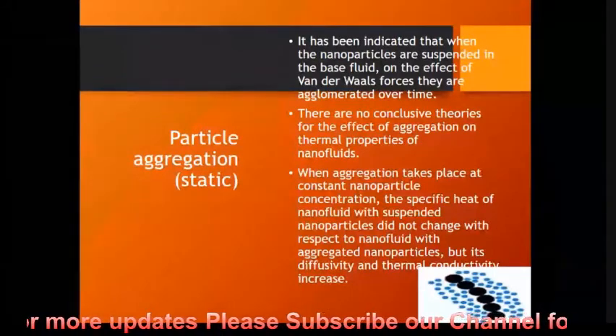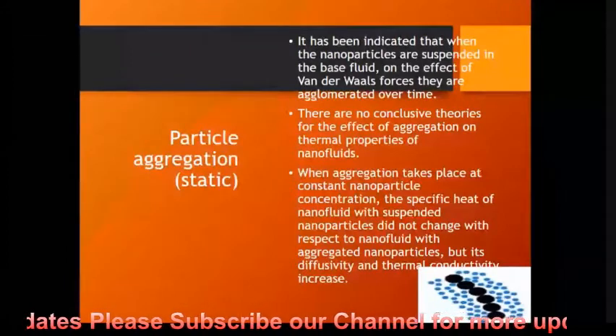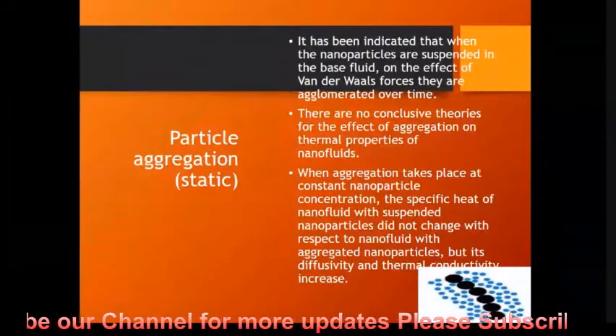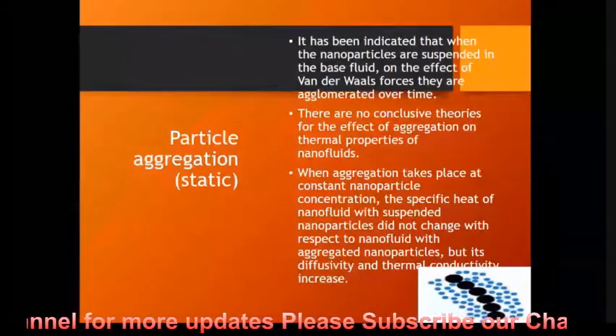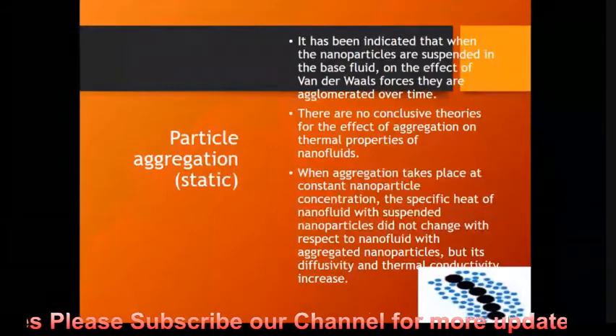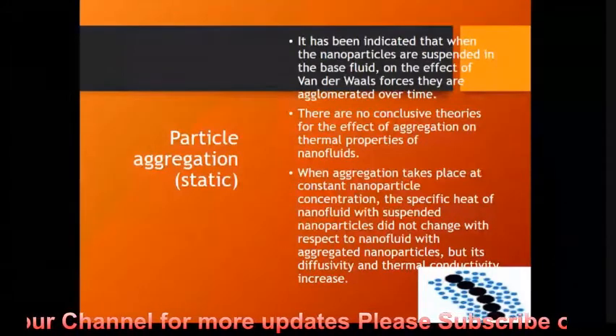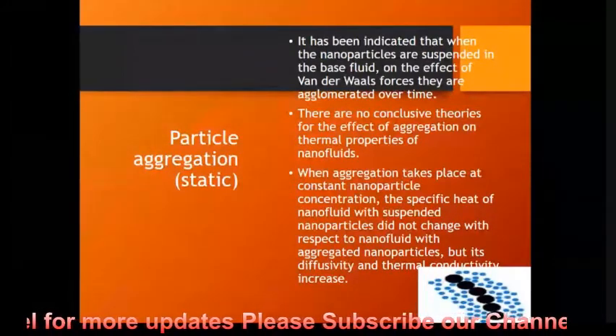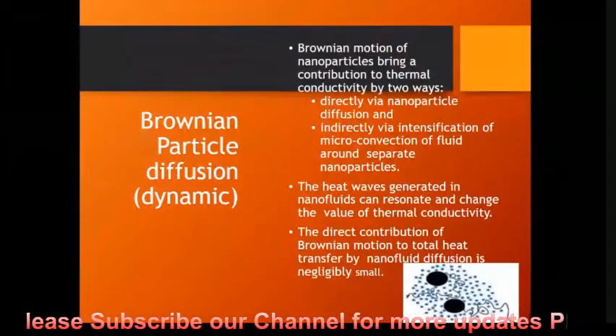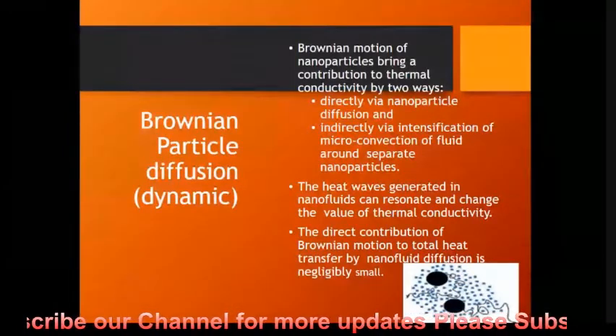So there are no conclusive theories for the effect of aggregation on thermal properties. So aggregation is something different from layering. Of course, layering is a very basic nominal thing to be done as far as the characterization mechanism is concerned. So it's a basic mechanism. We can very well go ahead. But as far as the particle aggregation system is concerned, this mechanism takes place at constant nanoparticle concentration, and the specific heat of nanofluid with suspended nanoparticles did not change with respect to nanofluid with aggregated nanoparticles, but its diffusivity and thermal conductivity will increase. Of course, we have already covered the Brownian particle diffusion also in the dynamic stage. So we have the static stage and the dynamic stage in the aggregating as well as layering stages.